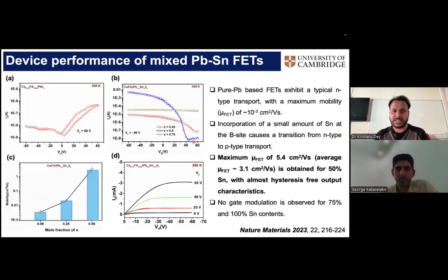But this trend completely reverses when you use some bit of tin in there. You now see that the current increases when you are going mostly in the negative voltage regime. That means you are inducing the oppositely charged holes now in the channel. So it's a p-type transport now. We see that introducing tin changes the polarity of your transport, so it makes it predominantly hole transport, and the mobility also increases steadily. The maximum mobility we can reach is 5.4 centimeters square per volt second, with very little hysteresis in the output characteristics, and I'll talk about that in a little more detail later. And these numbers are still the highest for this kind of composition.